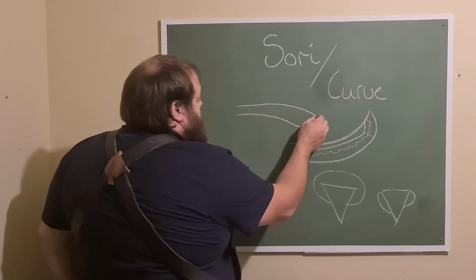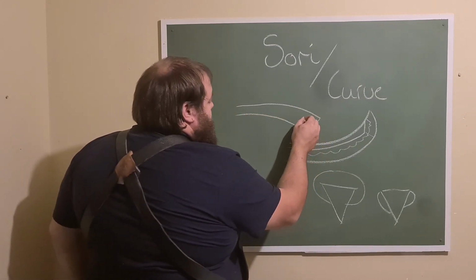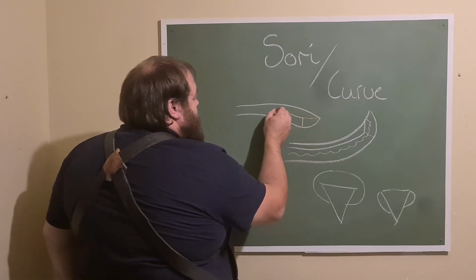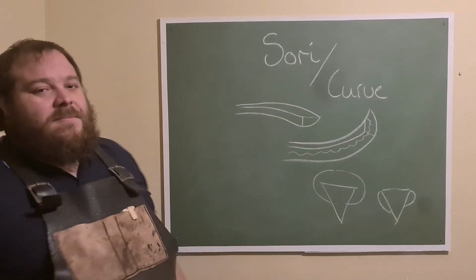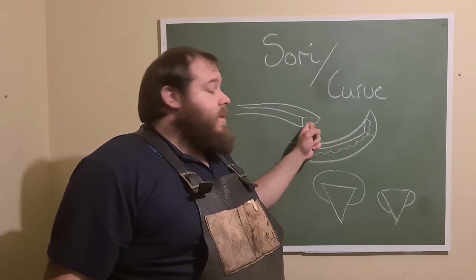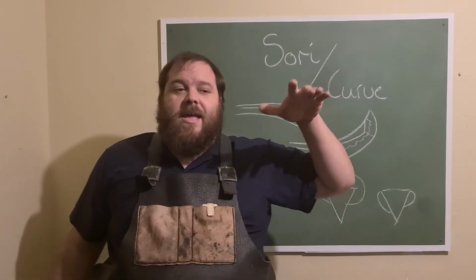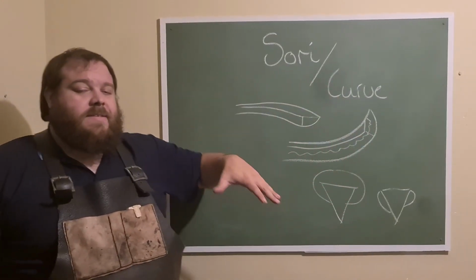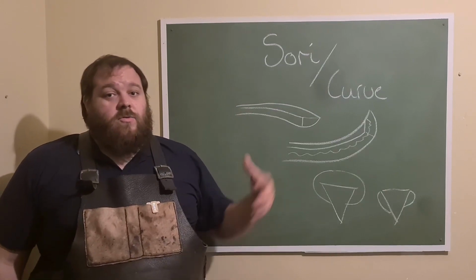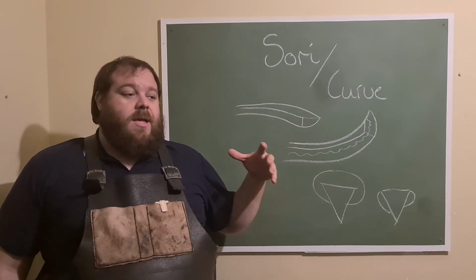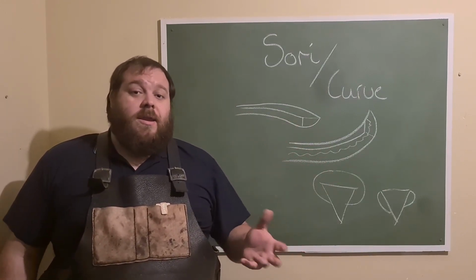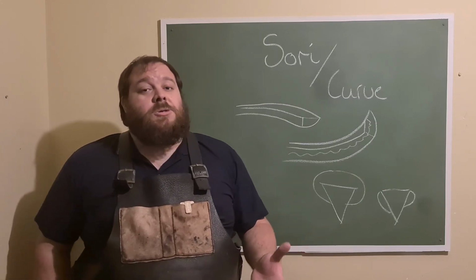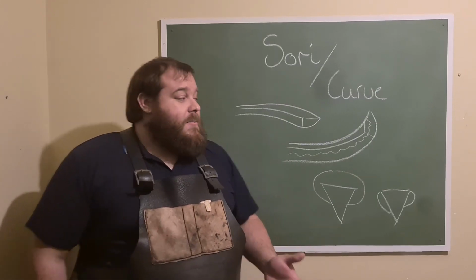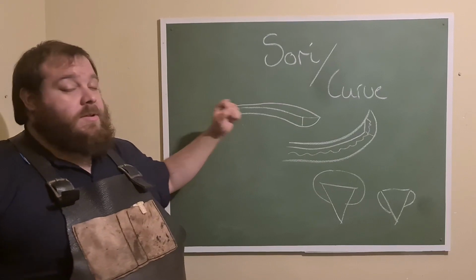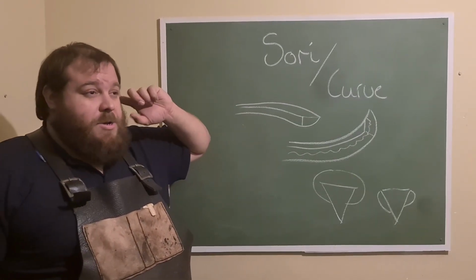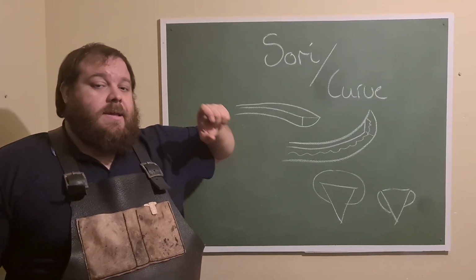And I know the comments I am going to see are going to be great. But in the event you end up with counter curve like this, then the only way to fix that is to reheat treat, to reforge, to reheat treat, to straighten it out before you do another quench. And you obviously have to do your normalization cycles before you do that again. But counter curvature happens a lot in oil quenches, especially with long, narrow blades.